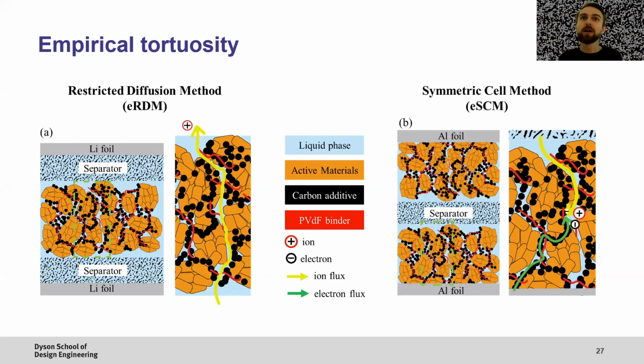In this paper, we looked at 2 empirical methods for measuring tortuosity factors. This one, Dean Wheeler did a lot of work on, where you put your porous medium of interest, could be an electrode, could be a separator, between 2 conductive foils, and then you build a concentration gradient, let it relax and measure it and work out how difficult it was to get through that pore system. And the other one is just having a conventional symmetrical cell with pores on both sides and extracting from your impedance spectra what the transport related obstruction to movement was based on both of the electrodes, i.e. the ones on either side of the separator.